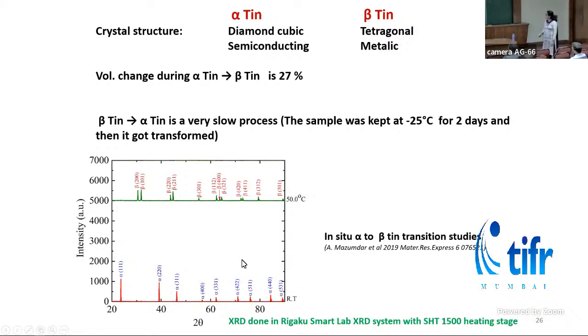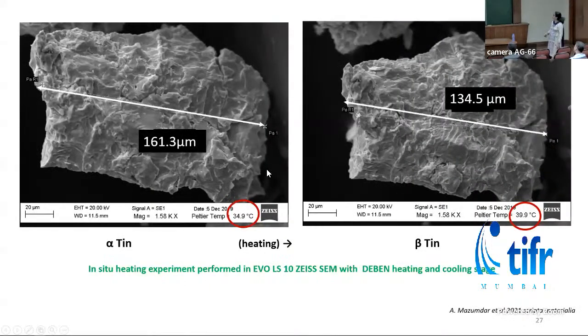This is an X-ray diffraction pattern of this sample at room temperature. By indexing the peaks, we can clearly see that this is alpha tin. And when the sample was heated to 50 degrees in situ, we could see that the alpha tin has transformed to beta tin by indexing this XRD line. But can we see this in SEM? Yes, we have made an attempt.